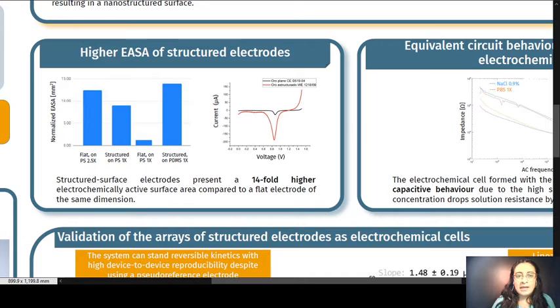We wanted to determine the electrochemically active surface area. To do this, we submerged the analyzed electrode into a diluted sulfuric acid solution, and we applied cyclic voltammetry sweeps. To determine the electrochemically active surface area, we integrated the peaks and normalized. We found a 14-fold higher electrochemically active surface area in the structured electrodes compared to flat electrodes with the same dimensions.